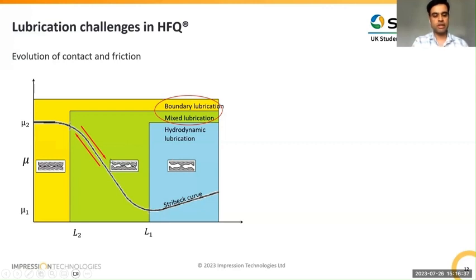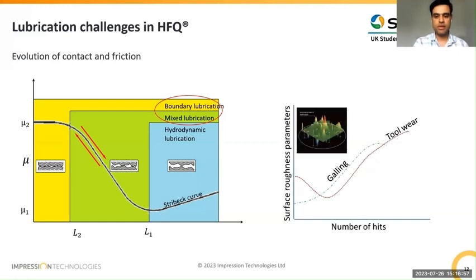But what can happen with the contact that is constantly evolving is, depending on the lubricant, the type of aluminium blank, and the forces and speeds that are used, the friction can either increase or decrease during that contact. And that is a dynamic nature that is very hard to predict for some tribo systems. Then, as we keep pressing the parts, let's say we press 4,000, 5,000 in a production run, galling, which is adhesive wear, also kicks in. Then tool wear also kicks in. So even between the number of hits and time over the production, the contact is evolving. So the friction is evolving, the contact is evolving. So how do you then quantify a system like this?